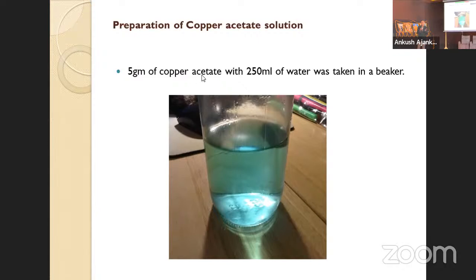We have to heat it at an average temperature of 70 to 80 degrees centigrade. After further heating for nearly 1 hour, its color will change into dark green, and when its color has converted completely to dark green, we have to keep it aside for cooling. After cooling it, we have to filter it using filter paper.